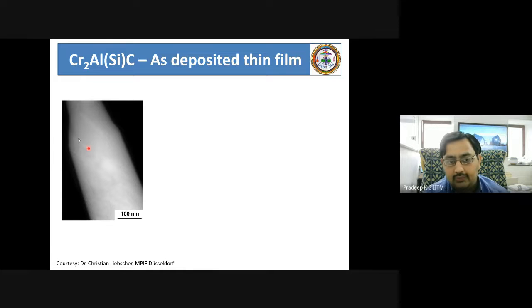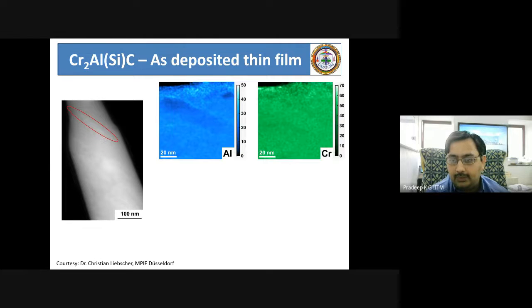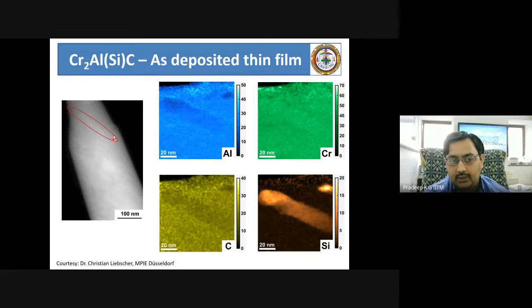Now you see the contrast variation within this needle in a 3-dimensional form, but there's a projected image in a microscope. You see the light region, which is probably responsible for a higher amount of silicon present inside. You do the chemical mapping, then you suddenly see that in all of these regions where there is light color contrast, you see a significant amount of silicon enrichment. So it's no longer the V-shaped attraction, it is more like a 3-dimensional nanoscale precipitate formation that you see from an EDS map of an atom probe needle imaged using a transmission electron microscope.